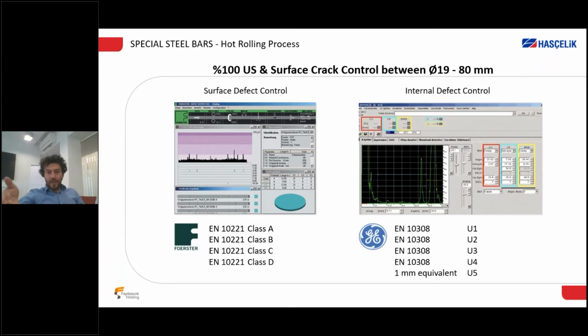And we have two control lines. One is surface defect control, one is internal defect control. So surface defect control is based on magnetic flux linkage. And internal defect control is based on rotating water. So we are capable to guarantee from class A for surface defect control up to class D. And for internal defects, we are capable to guarantee from ultrasonic class 1 up to 4.